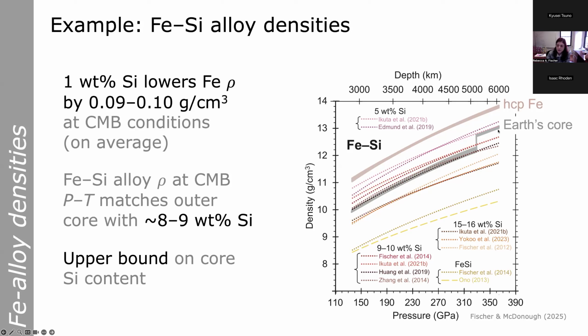So in gray is the Earth's core density. This pink shaded region is the density of solid iron. And then all of these thin colored curves are calculated from equations of state from a bunch of different studies looking at iron silicon alloys with different silicon contents. And if we look at them all together, we find that on average, adding 1 weight% silicon to iron lowers its density by something like 0.1 grams per cubic centimeter.